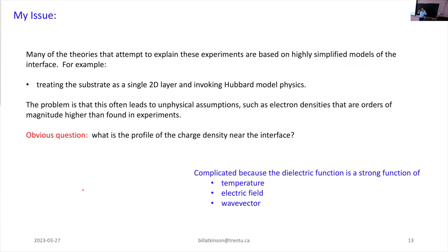And it makes the problem tractable. It's something you can solve, but it may be putting you in a regime where the physics is completely unrealistic. So the classic example of this in my mind is when you cram all your electrons into a single 2D layer and then invoke Hubbard physics. The problem is you're getting charge densities that are one or two or three orders of magnitude larger than actual densities in these substrates. And that tends to really overemphasize the role of Hubbard physics.